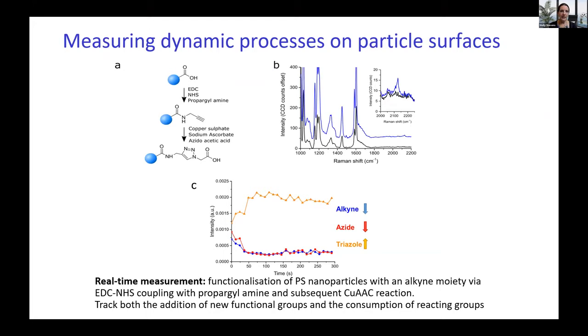What we're showing in this image here is how we can also measure dynamic reactions, dynamic processes on individual particles, which I think is really, really exciting in terms of some of the things we can now study using this approach. And the exemplar that I've shown here is where we're trapping, at the top left in panel A, an individual polystyrene particle, and we perform a first chemical reaction to introduce an alkyne group, and this shows up with a really nice characteristic peak in the Raman spectra. And then we can do a second reaction to convert this to a triazole, and so you then see a decrease in the alkyne peak and an increase in the triazole. And you can monitor that for individual particles and really follow those reactions, which is very, very exciting.